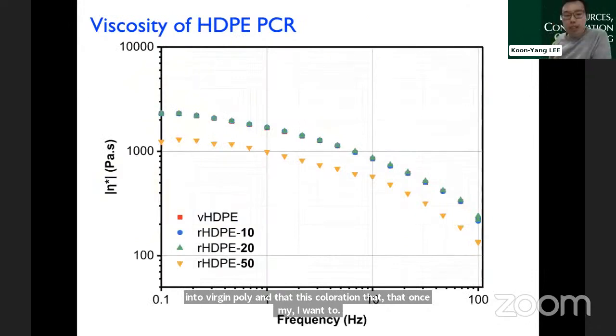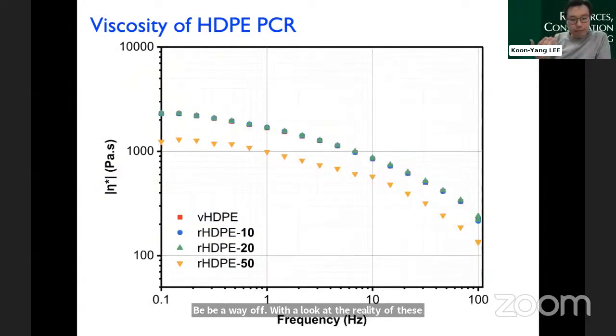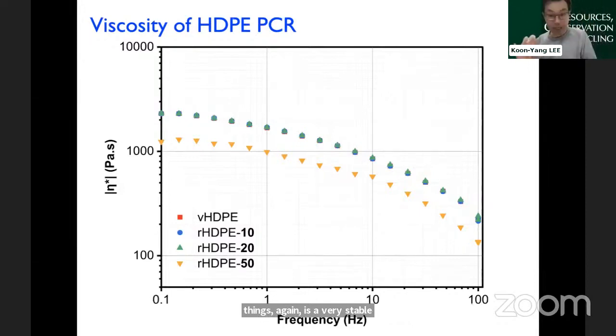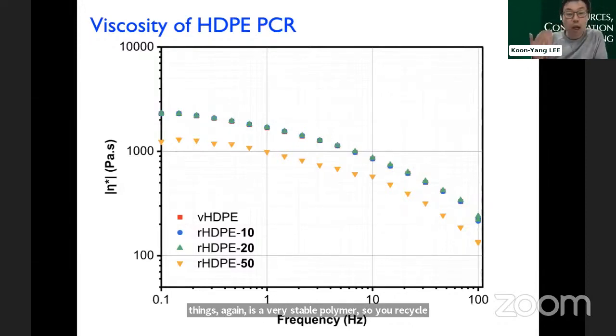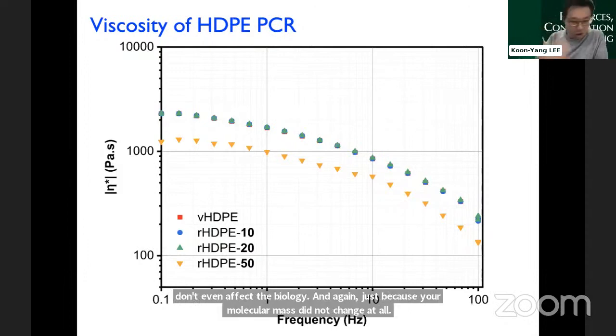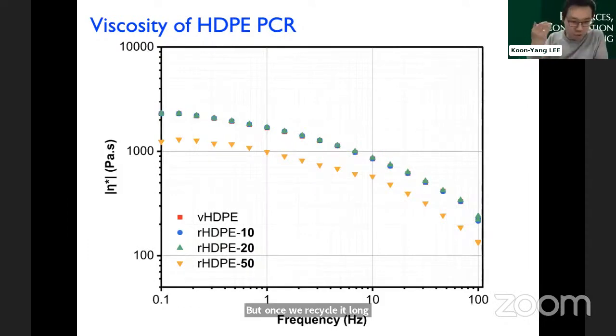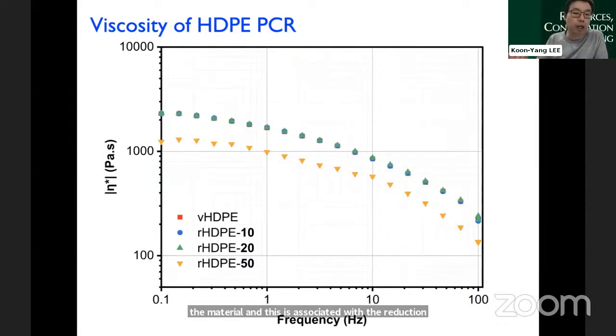We then look at the rheology of these things. Again, polyethylene is a very stable polymer, so you recycle it 20 times, you don't even affect the rheology. And again, just because your molecular mass did not change at all. But once you recycle it long enough, in this case 50 times, you see a decrease in the complex viscosity of the material. And this is associated with the reduction in the molecular weight of these polymers. So yes, polyethylene will degrade if you do recycle it, severely.